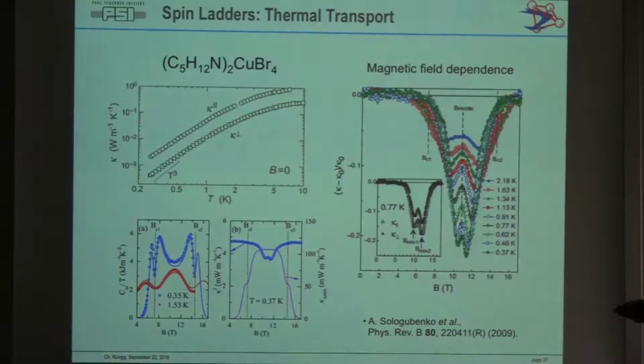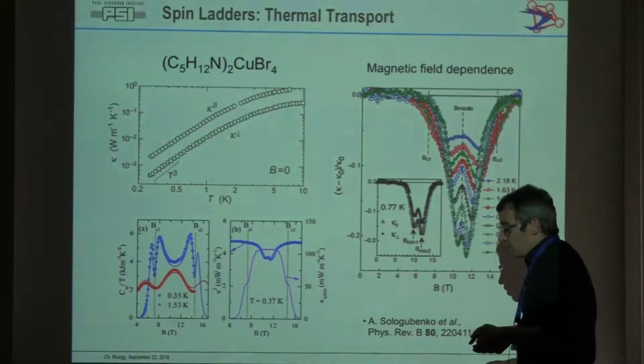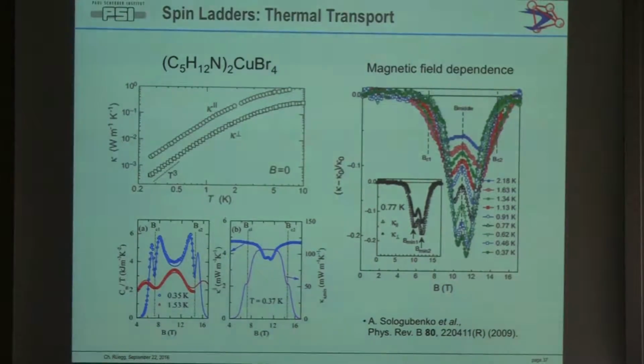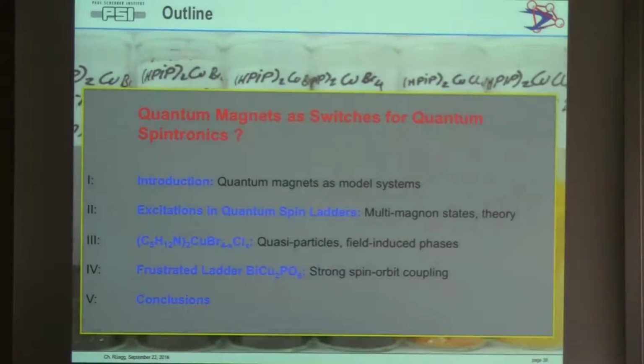My feeling is that the measurements were done by a super expert group, Thomas Lorenz, and Sologubenko, who did some of the measurements presented before. So there's no doubt that this was done in a very good way. But on the other hand, there are maybe problems with how we contact this kind of metal organic samples. The chlorides may react with some of the things we use. There's maybe more to be tried.